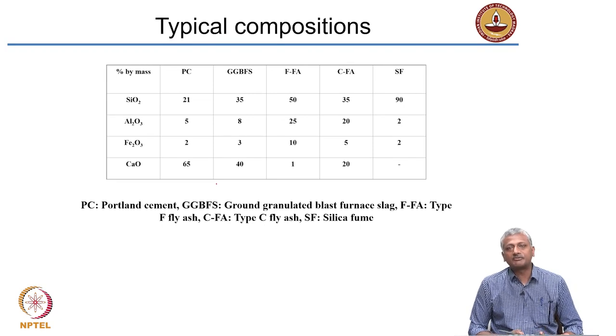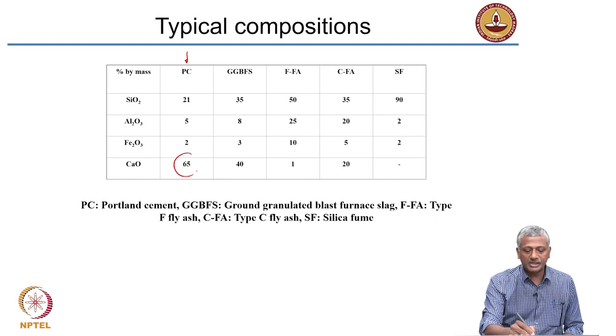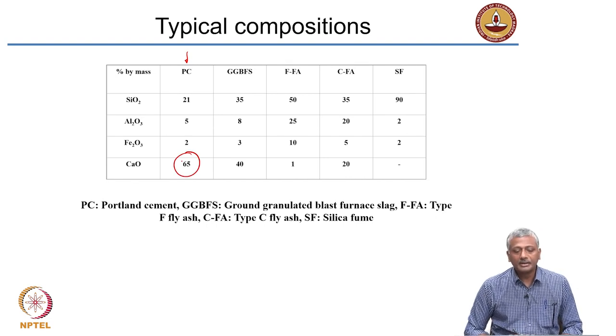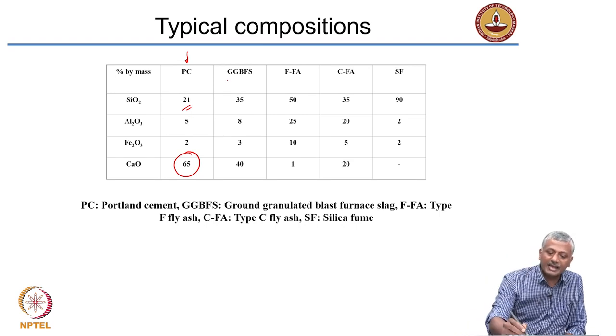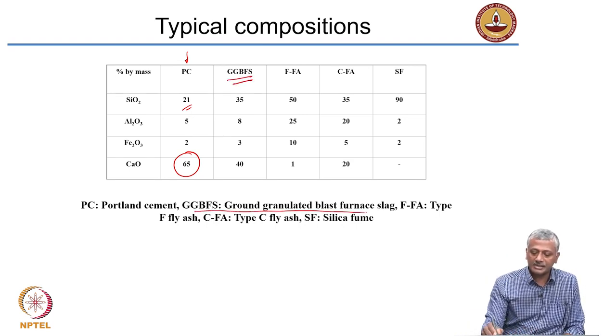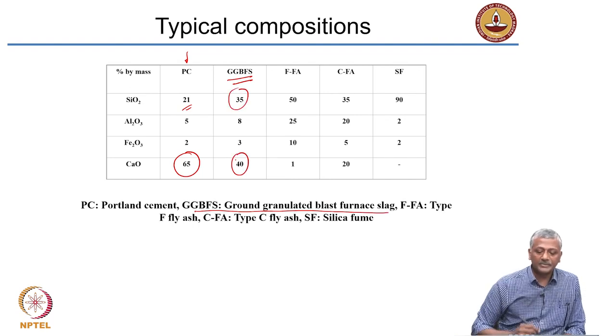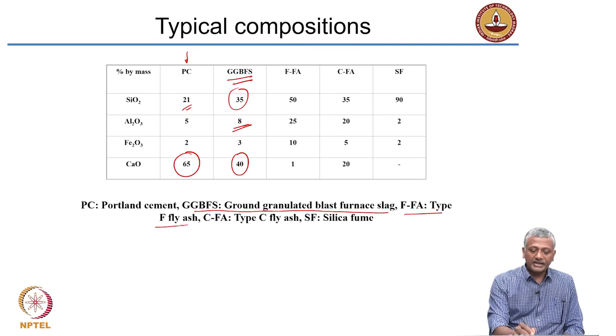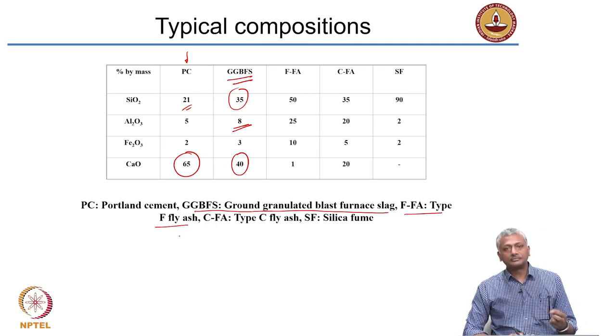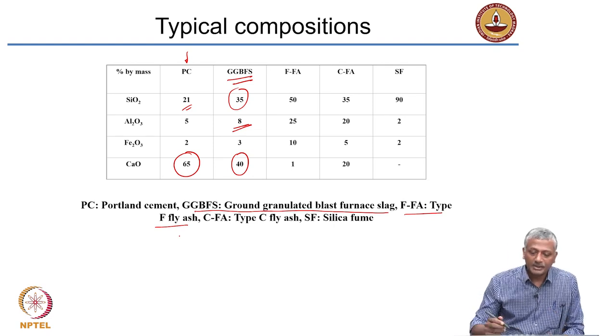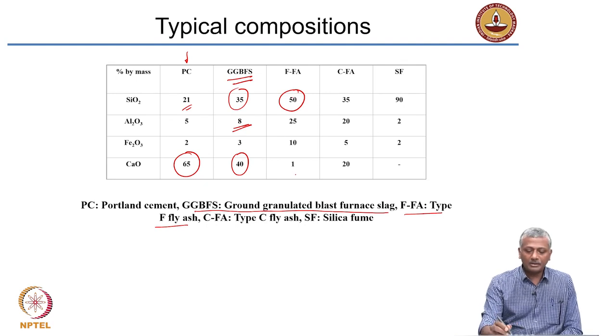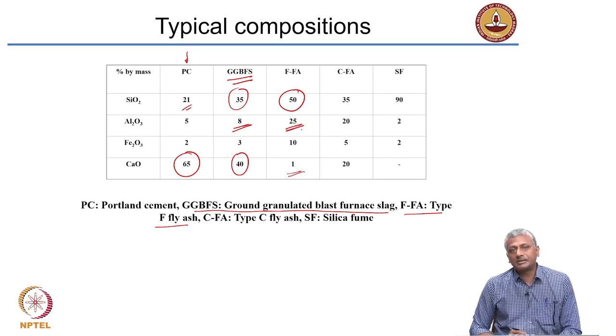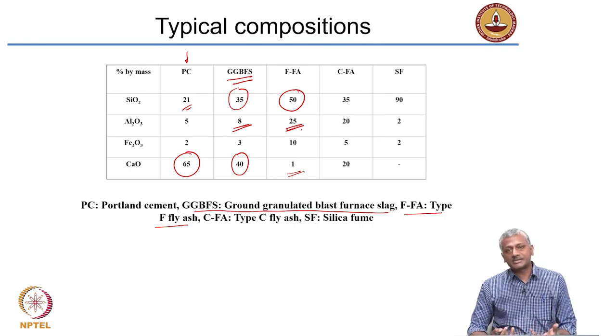To give some examples of typical compositions: cement is mostly composed of calcium oxide, with less silica, alumina, and other oxides. Ground granulated blast furnace slag has nearly equal quantities of silica and calcium oxide with significantly higher quantities of alumina. Type F fly ash, generally obtained from burning semi-bituminous coal, has an extremely high amount of silica and almost nil calcium content, plus a very high amount of alumina — it is a silicoaluminate similar to clays but not as reactive.